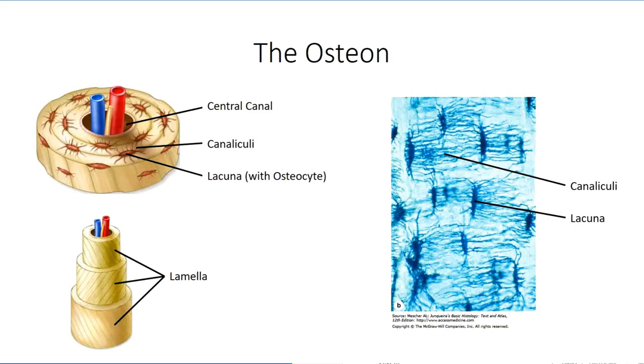While cartilage has a uniform matrix, mature bone tissue is much more organized into functional units known as osteons. The osteon is a long cylindrical structure which resembles a tree trunk in cross-section, containing four to ten concentric rings of bone matrix with bone cells embedded in lacunar cavities between each ring. The lacunae are interconnected through porous channels called canaliculi, which contain cytoplasmic extensions allowing communication between cells throughout the osteon. Each ring is formed independently, with outer rings serving as a scaffold for inner rings. The collagen in each ring is laid down in a spiraling fashion, with the direction alternating between adjacent rings to create perpendicular layers, generating great tensile strength against torsional forces in each direction.